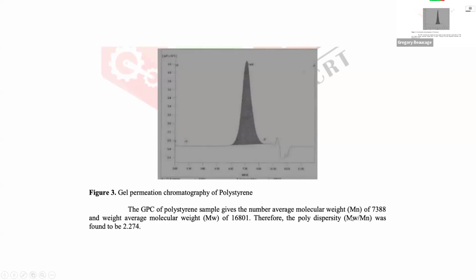So anyway, the ratio of the weight average to the number average gives you the polydispersity, which if this is a spike, all these moments are the same, and this is just one. And if it's broad, then the higher order moments, like the third, are larger than the second. So this becomes a larger number. Typically, in this case, it's 2.27 from a free radical polymerization. So it's a broad distribution of molecular weights. At the high end it's going to be 1 million, and at the low end it's going to be 10,000. So there's orders of magnitude difference in molecular weights.